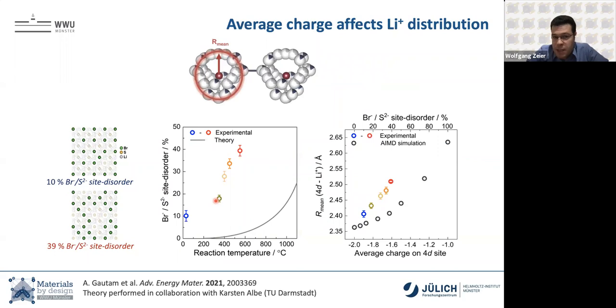Now let's bring this back to this R mean that I was talking about earlier, this average distribution. And here, this is another example where this R mean is a direct function of up here the site disorder, or down here the average charge on this central site. So the lower the central charge is, the further apart these cages are. And this is a much more meaningful study than looking at these chloride, bromide, and iodides, because we're now not changing the nature of the anion. Now we're just in the bromides. So the chemical composition of all these materials is the same, but we have an entirely different lithium substructure just by quenching, disordering these halides and the sulfide position.